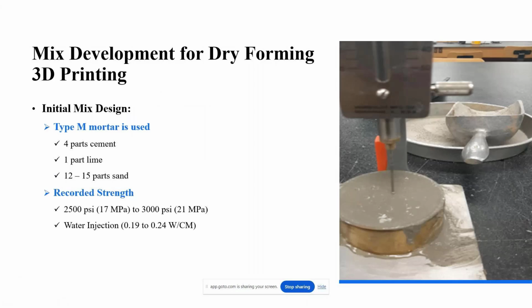So basically, in the research, we did some mix development for dry forming. Here we're having a little bit of challenges. First of all, how far could we go, or what's the distance in the X and Y direction between the straws where the infusion of water would still be efficient. We don't want the water from two consecutive tubes to overlap, otherwise it will be overhydrated, or we don't want these pipes to be so far away, otherwise there will be massive unhydrated portions, and definitely that will lead to the collapse of the formed body, or the 3D printed body, which is the 3D printed coral reefs.